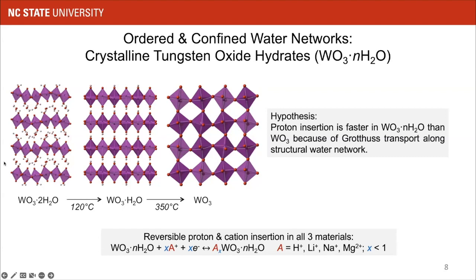These tungsten oxide hydrates, these are the structures, they're layered materials, as you can see on the left here, and we can go through several phase transitions within the hydrates, all the way to the anhydrous tungsten oxide. All three of these phases can undergo reversible proton and cation insertion. So they are all redox active.